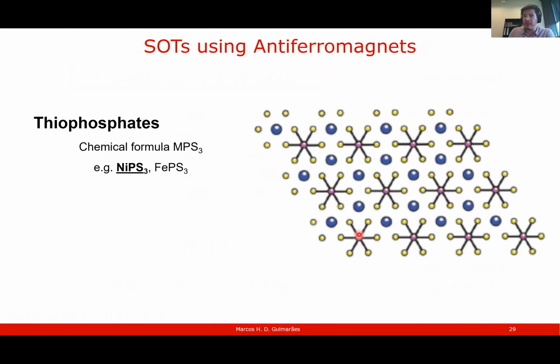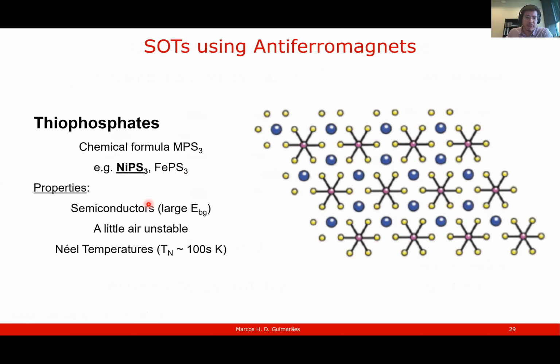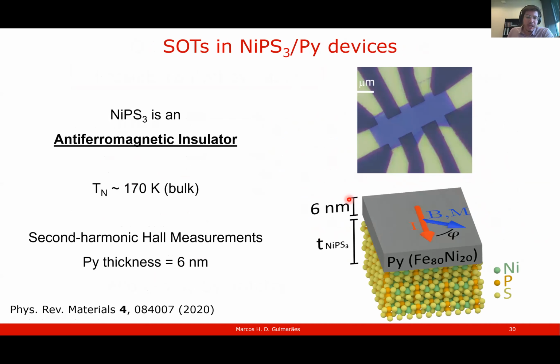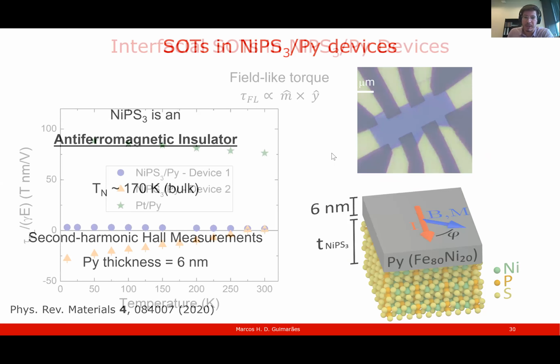Another way that would be possible is using magnetic control. So if you look at nickel thiophosphate, which is a semiconductor, so it has a relatively large band gap, so it's basically insulating for all purposes. It's a little bit air unstable, but we can work with it. And the Néel temperature, which we can cross going from room temperature down to liquid nitrogen temperatures, is around 170 K. And it gives a nice magnetic pattern like that. So I won't go into details. We measure the torques with a slightly different approach, but it's a non-resonant technique, but we can extract the torques nonetheless.